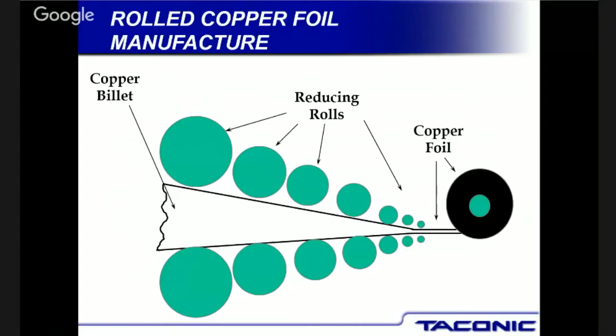There's a material called rolled copper, and that's typically the copper that's used on flex circuits. And we say it's rolled. How they manufacture it, they take a copper billet and draw it down between large rollers. As you roll it down, just like when you're making cookies with a rolling pin, the dough spreads out. In this situation, the copper spreads out to an 18-inch or 24-inch wide sheet, and then the copper is reeled up on a roll at the end. The surface roughness in that copper is basically the roughness of those last two little rollers that it hits.